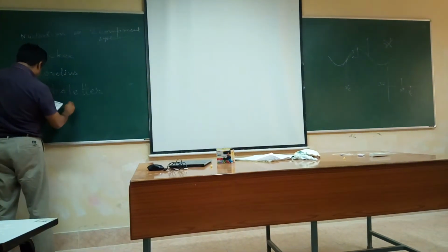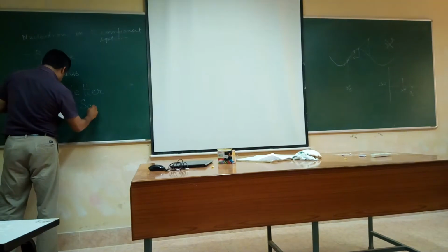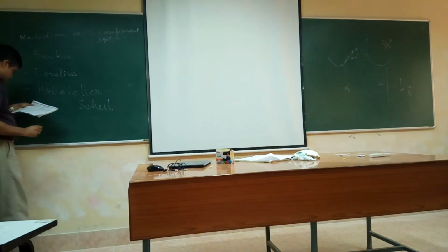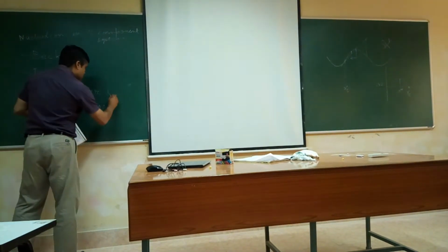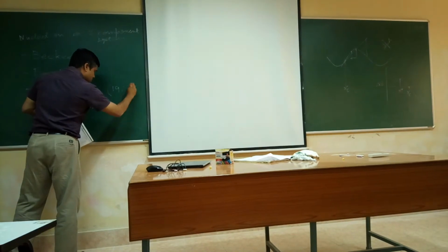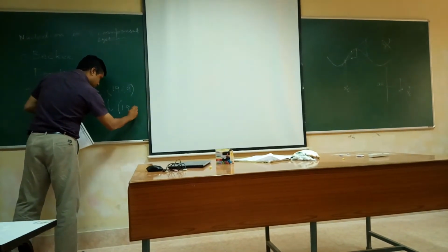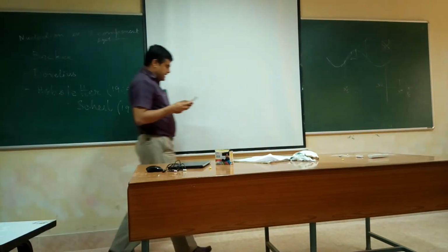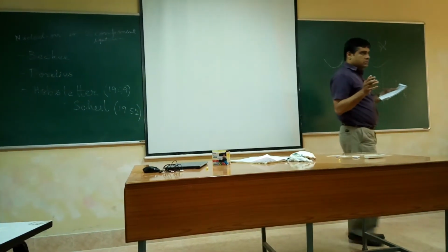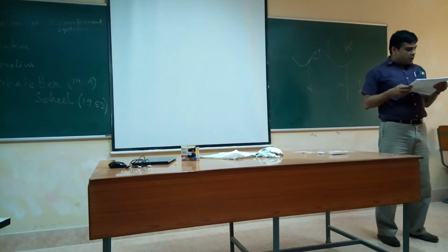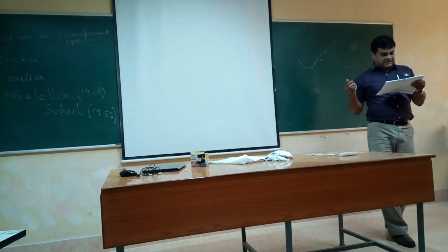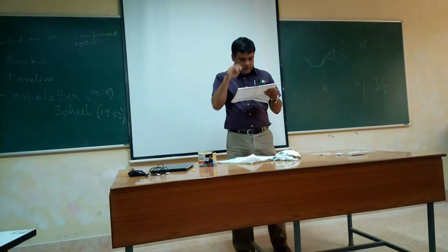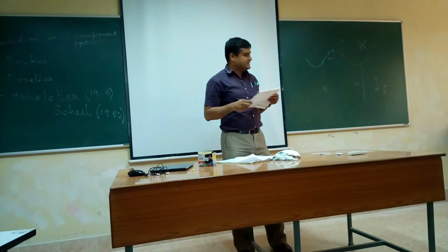Hobstetter and later Scheil attempted to combine the Becker and Borelius models. They assumed that the most probable nucleus is that combination of size and composition requiring the least free energy of formation, taking into account both surface energy gamma and delta G beta.